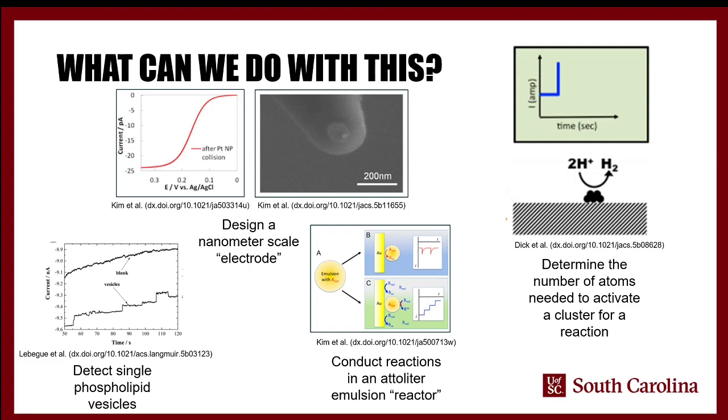With this technique, a couple of colleagues of mine from the University of Texas actually developed a way to take a relatively small tip to start with, but then put down an insulating layer of titanium dioxide, and then reduce via tunneling a single platinum nanoparticle.